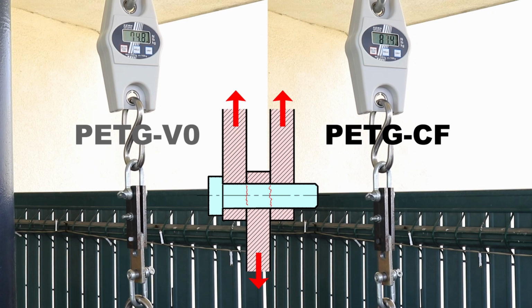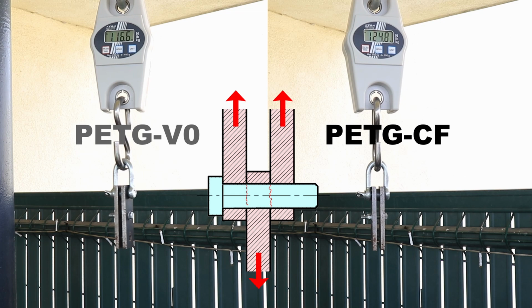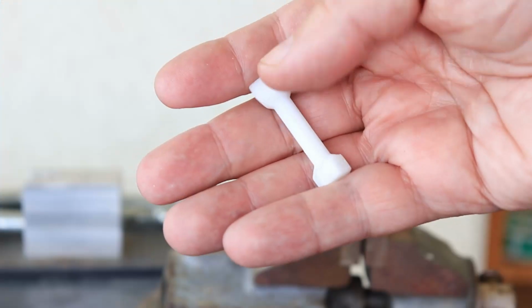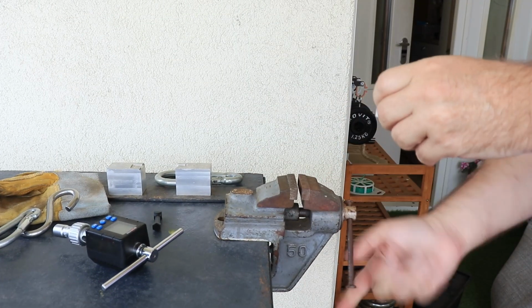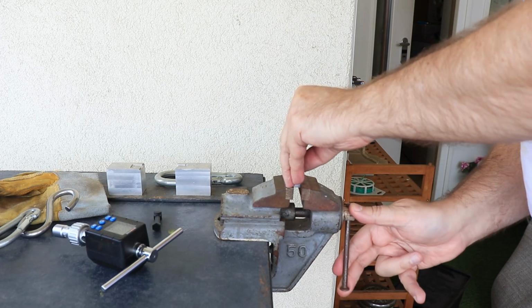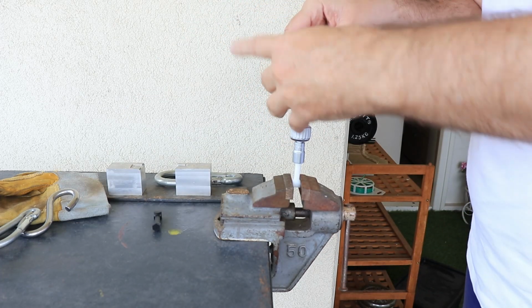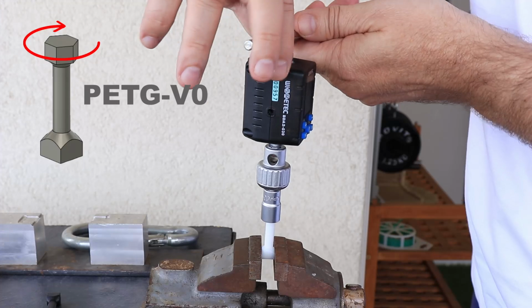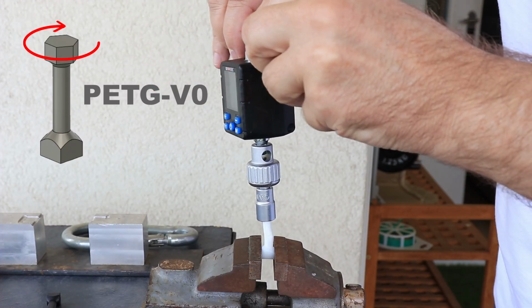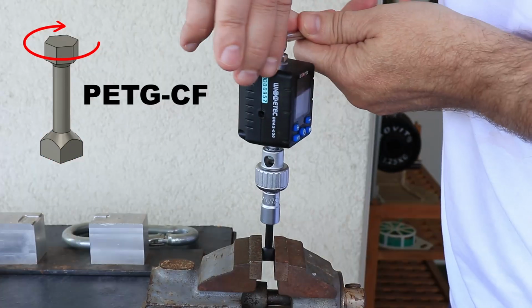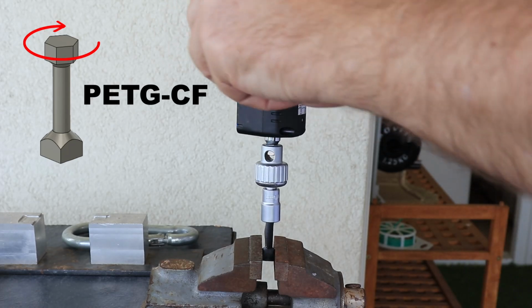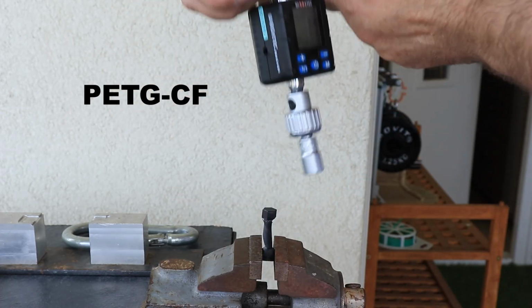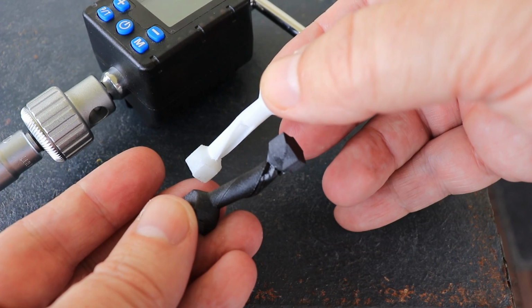And this is the shear stress, two-sided shear stress. And they are very similar in this test. And now the torque or twist test, where I want to measure the load at 90 degree angle and the maximum load. And I'm starting with the V0. 0.9 newton meters, and this was the max too. And with carbon fibers, the max was 1.1.